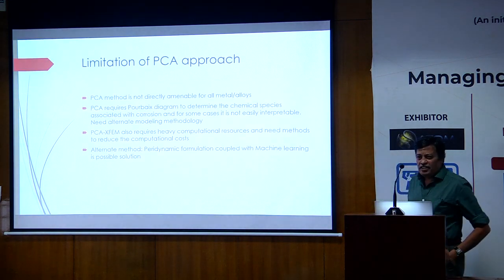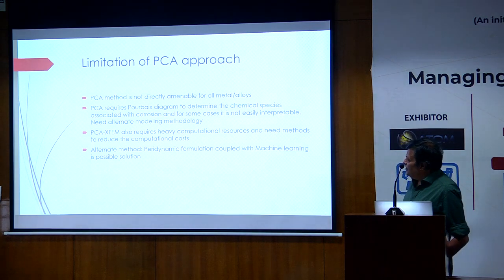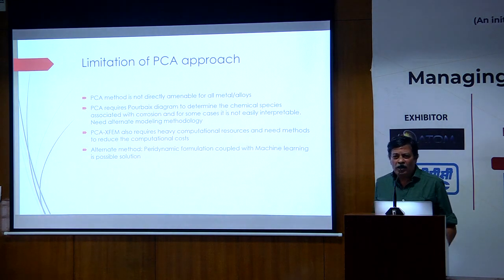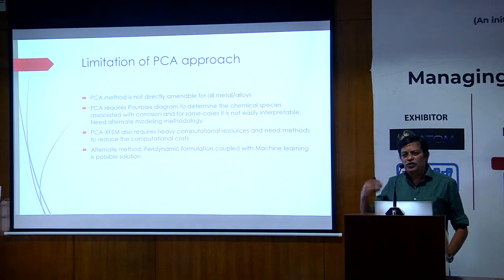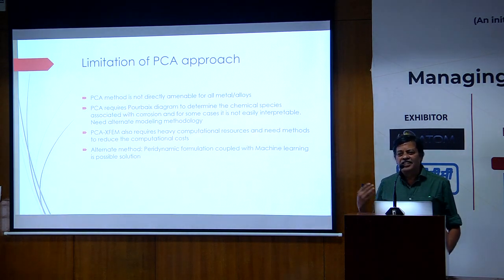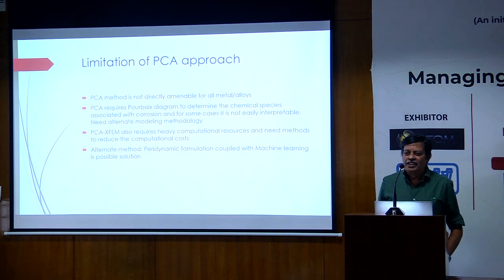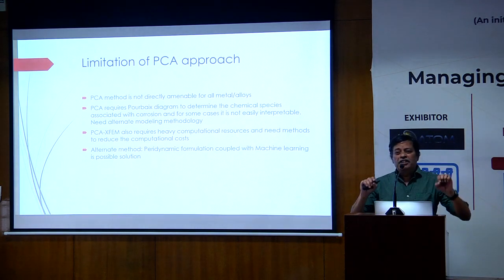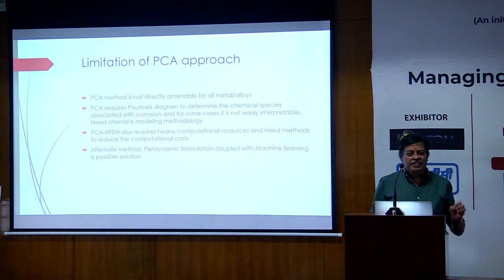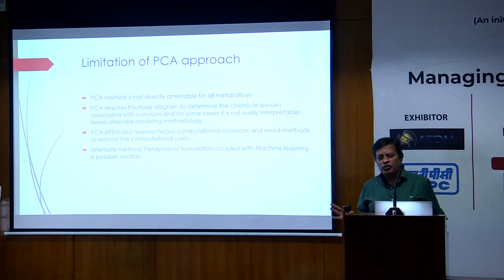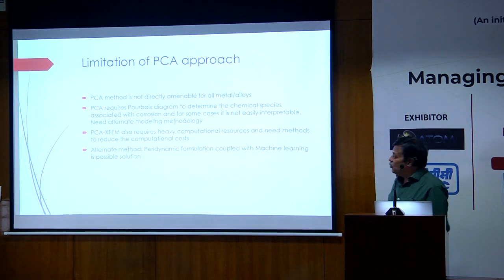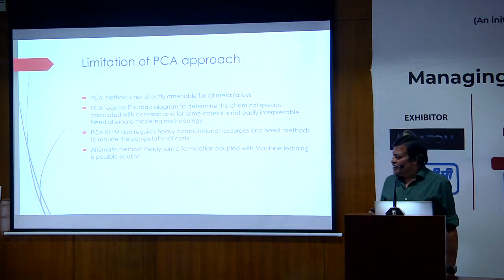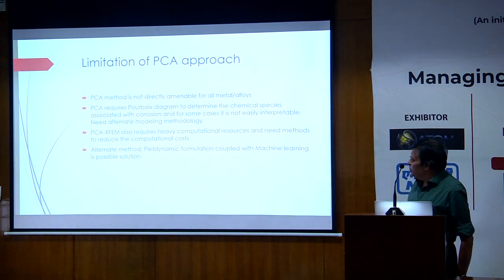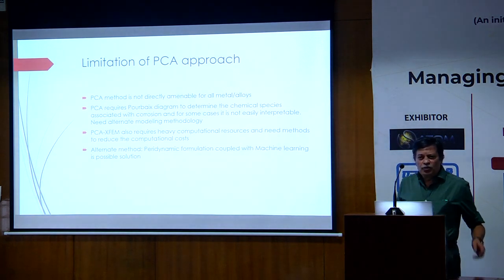Okay, what is the limitation of the probabilistic cellular automata? The PCA is not directly amenable for all metal alloys. Why? For example, for a nickel-based superalloy, if you get a Pourbaix diagram, you will see that there are a number of reactions which are redundant. That is, each of these reactions can be derived from others. So there are no clear-cut chemical species that we know that can be directly ported into my cellular automata to devise the corrosion rules. So this is one of the major limitations. We wanted to get rid of this. And also it requires heavy computational resources to model this whole thing.